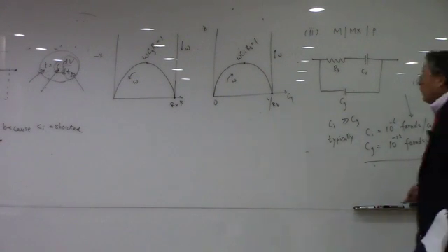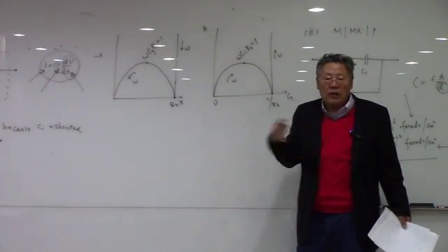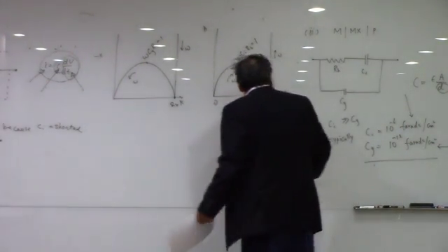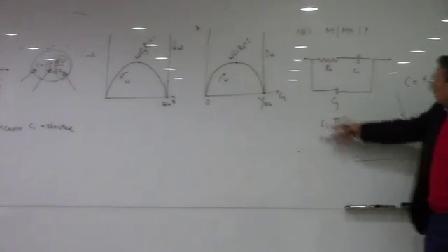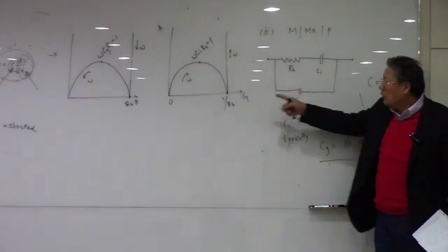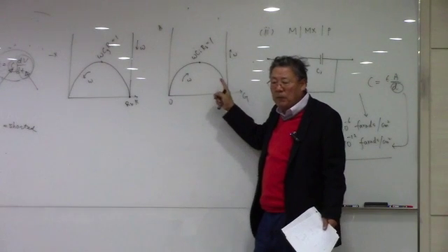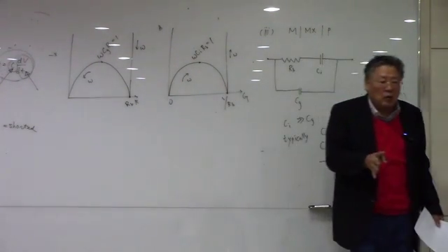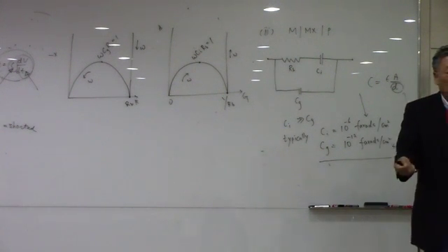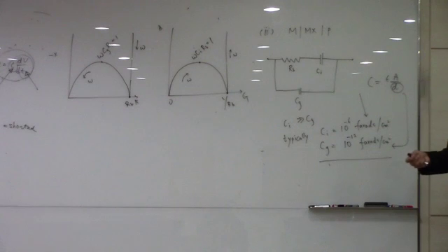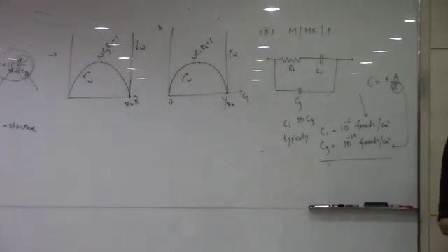So if you make a spectrum changing the frequencies from low to high in that blocking electrode system, okay, in this blocking electrode system, then you're going to have this profile and this profile, and from this you can determine the values corresponding to the bulk resistance and the double layer capacitance and geometric capacitance separately. This is beautiful, isn't it?